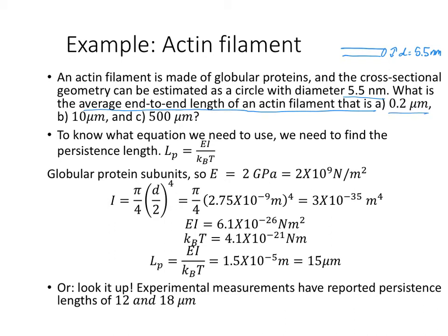In order to ask this, we learned in the last slide that the end-to-end length depends on the persistence length. And so we need to first calculate that. In this case, we've been told something about the geometry of the material. This allows us to calculate the persistence length from the flexural rigidity and from thermal energy. We're able to use here that the Young's modulus of proteins is around 2 gigapascals. We then calculate the moment of inertia